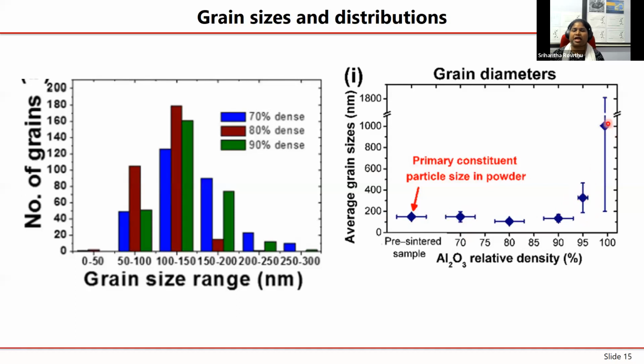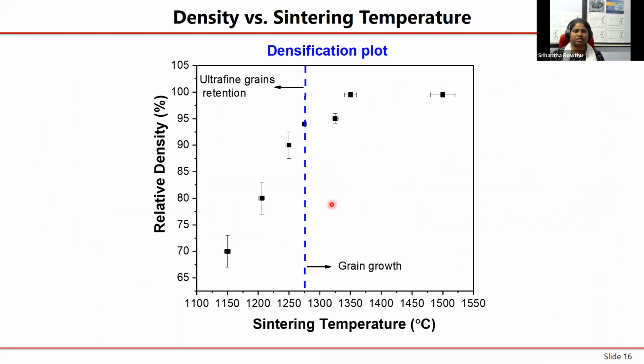However, for the 99.5% density, which was this particular case here, the grain sizes are almost around 1 to 2 microns. So it is no longer in the nano size, but almost like micro-sized grains. Now, if you look at this sintering plot, that is, if you plot the relative densities as a function of sintering temperature, as I just said, below a particular temperature your ultra-fine grains are retained, but beyond that particular sintering temperature, there is a grain growth that is happening.